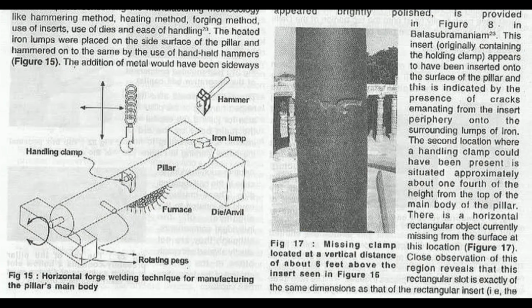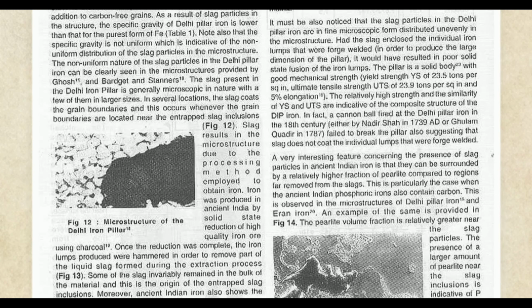This schematic illustrates the pillar's mechanical assembly. The extracted iron lumps were heated in charcoal and joined using horizontal forge welding. Hammering squeezed out most of the liquid slag, while permanently trapping microscopic slag particles deep inside the metal's solid body. This cross-section reveals the resulting physical structure, a metal matrix composite produced by these forging conditions.